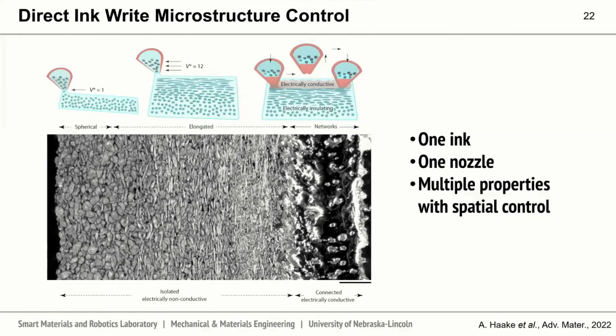With this, we are not only able to change from spherical to elongated droplets, but we can actually create connected networks from any of these microstructures within the materials. This is enabling in that we're able to use a single ink, one nozzle, and achieve multiple properties throughout a printed part with spatial control.